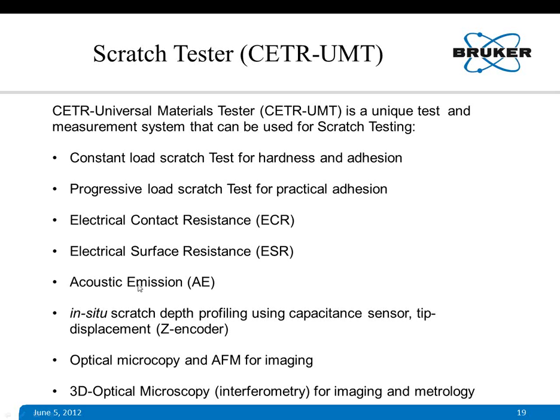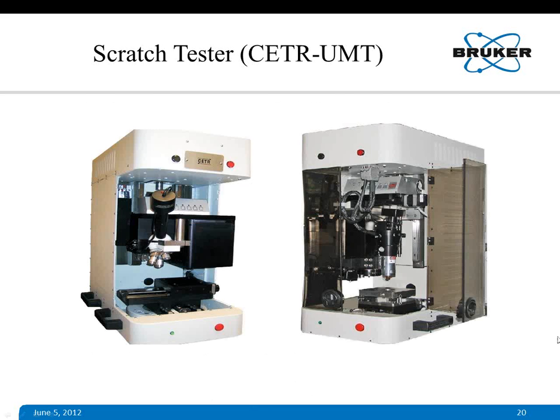Acoustic emission, in situ scratch depth profiling using a capacitance sensor, which measures the depth of the coating when it scratches, as well as the scratch depth and tip displacement. This is another parameter which can be measured in situ to have the profile of the scratch. Optical microscopy and AFM for imaging after the scratch is done, and 3D optical microscopy, which is related to interferometry. This is also used for imaging and metrology of any scratch.